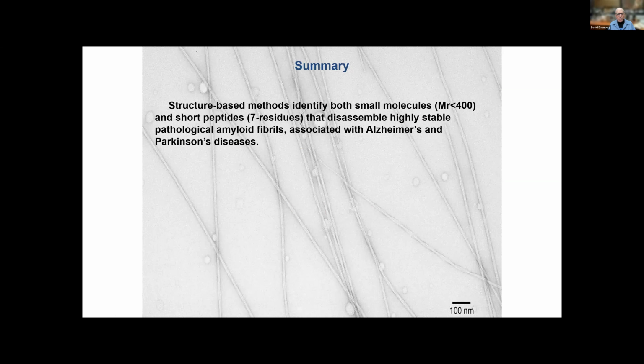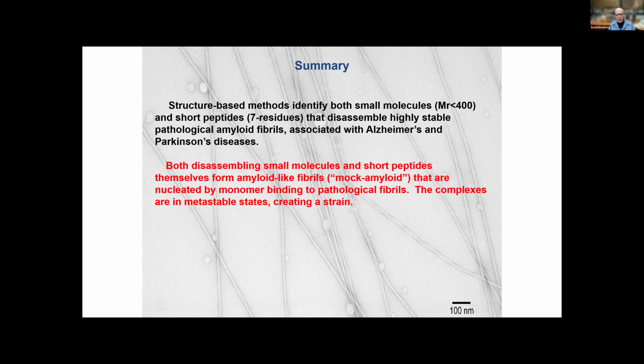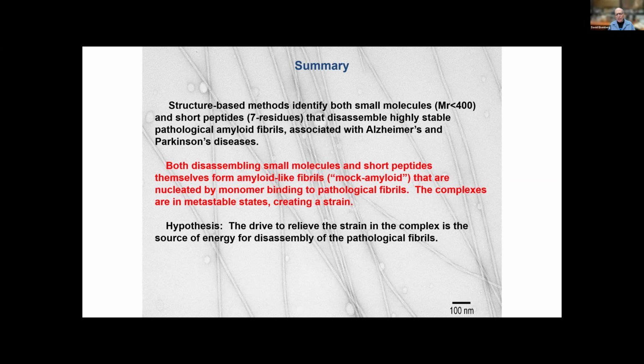So just to summarize, these structural methods have identified both small molecules and short peptides, 7 residues, that disassemble these very highly stable pathological amyloid fibers associated with Alzheimer's and Parkinson's diseases. Both the disassembling small molecules and short peptides themselves form amyloid-like fibers. We call them mock amyloid. They're nucleated by monomer binding to the pathological fiber. The complexes are in metastable states, creating a strain, and our hypothesis is that the drive to relieve the strain in the complex is the source of energy for disassembly of the fibers.